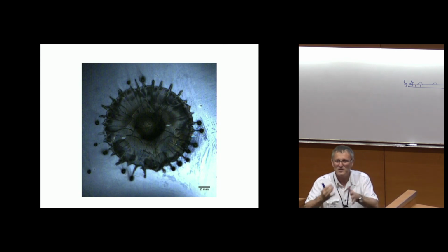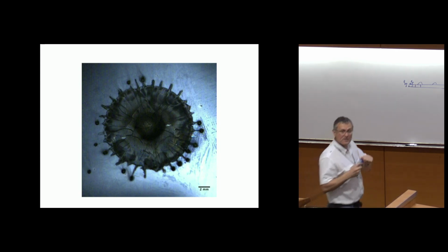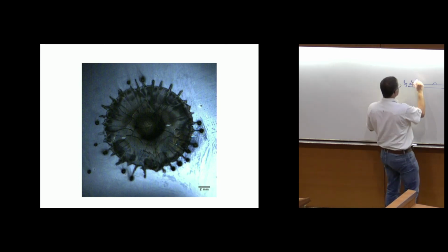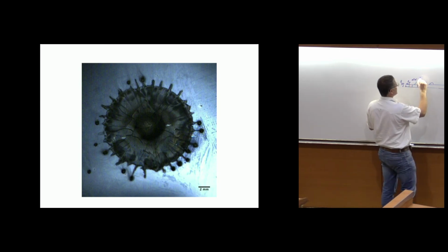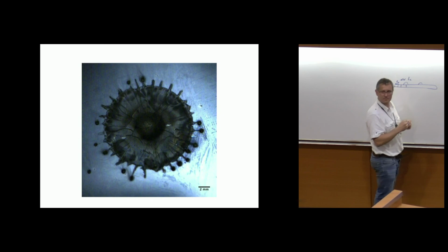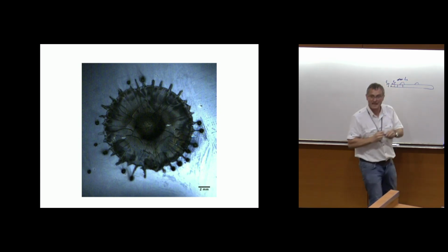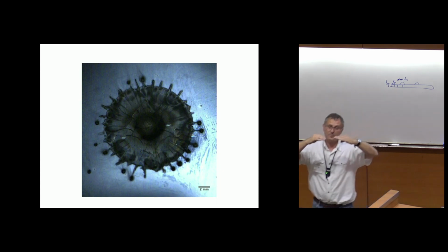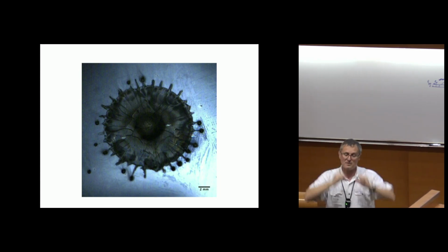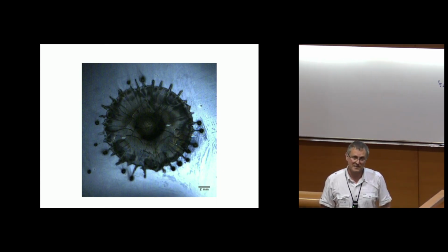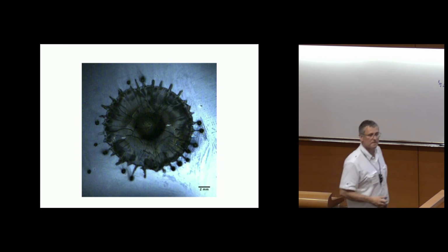In the other case, for some reason, it explodes much before. Also, here HP is about the same as the Griffith length, while in the other case the Griffith length is much smaller than the liquid thickness. So there is a difference.